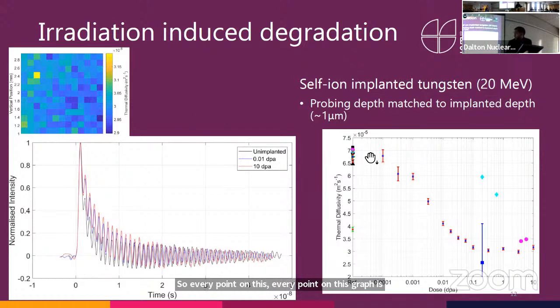And we did see a degradation in thermal diffusivity, which started to saturate around 0.01 dpa, and by 0.1 dpa it was completely saturated.